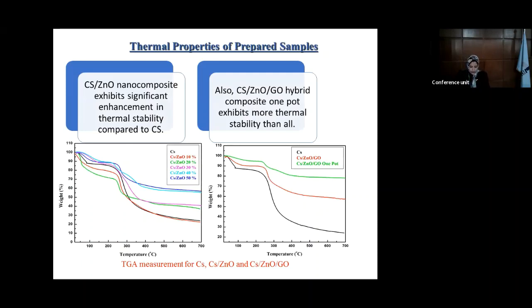This result showed that the chitosan zinc oxide nanocomposite and chitosan hybrid composite had higher residual mass percentage relative to the presence of zinc oxide and graphene oxide due to the rise in temperature. In addition, a certain improvement in the degradation behavior of the composite relative to chitosan changed from 22 to 79 percent, which could decrease the degradation of chitosan with increasing the filler. And the highest percentage was for the one-pot nanocomposite. So the chitosan zinc oxide nanocomposite exhibits a significant enhancement in thermal stability compared to pure chitosan. Also, the hybrid composite one-pot material exhibits more thermal stability than all other samples.